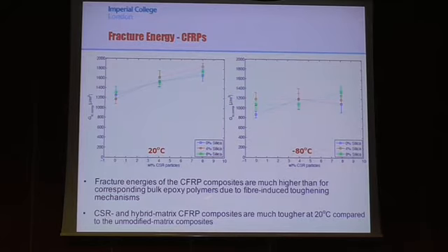We see that the fracture energies of the carbon fibre polymers are much higher. Our control system, which is the blue dot here, is at 1250 joules per meter squared. So the fracture energy of the carbon fibre polymers is much higher than the corresponding bulk epoxy polymers. This is due to the influence of the additional fibre toughening mechanisms, but also when we add in the CSR particles and the silica particles, we do see some toughness increases. So there is some transferability of toughness from the bulk polymers into the composite systems, especially at 20 degrees.